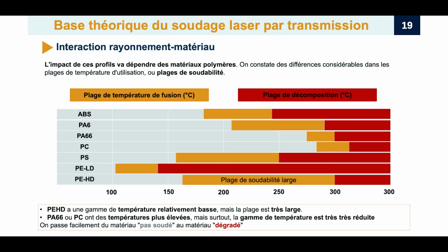So the weldability window is that specific temperature range sandwiched between T-flow, I gotta reach it, and T-deg, must not exceed it. That's the zone. You have to get the interface temperature into that window and keep it there for the required reptation time to get a good weld. Keep it in the Goldilocks zone, not too cold, not too hot. Exactly. Only within that window will the weld bead form properly, be structurally sound and homogeneous, and the heat-affected zone around it will be stable and controlled. Stray below T-flow, unwelded; push past T-deg, degraded and brittle.